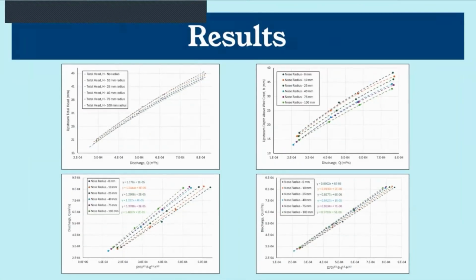The top graphs showing upstream total head and depth above the weir crest versus discharge illustrate that the smaller nose radii result in higher head and depth. This trend leads into the bottom graphs where the discharge coefficient, represented by the slope of the trend lines, increases with larger nose radii, improving hydraulic performance over the weir.